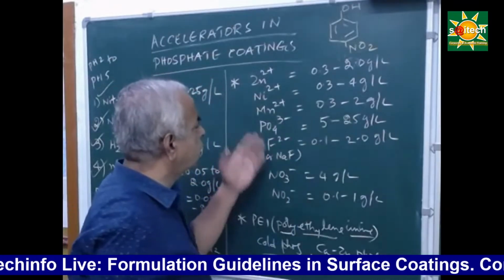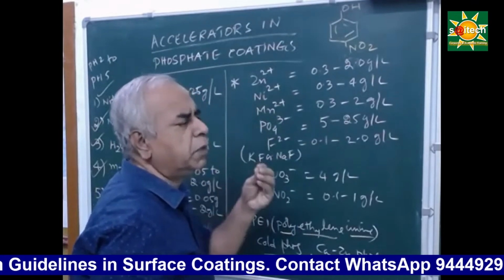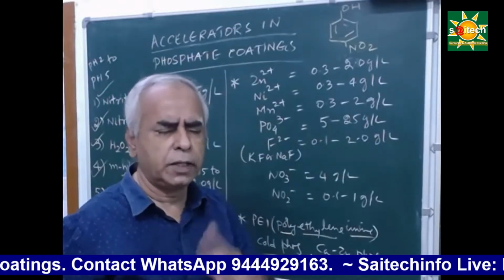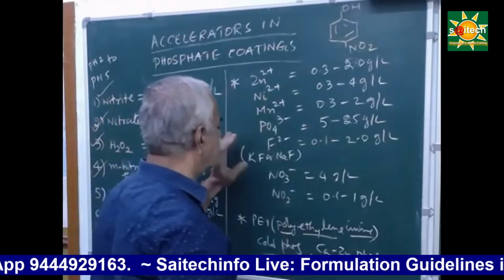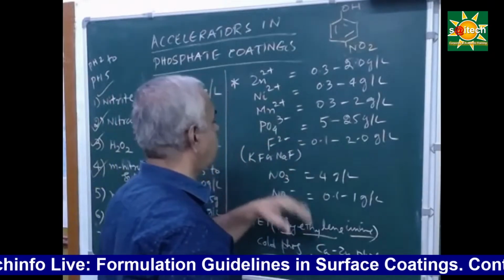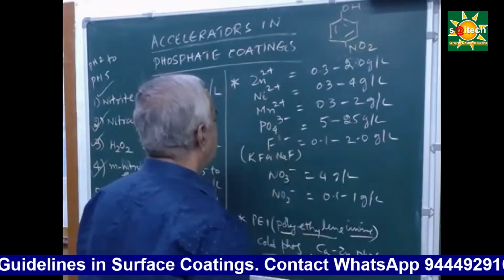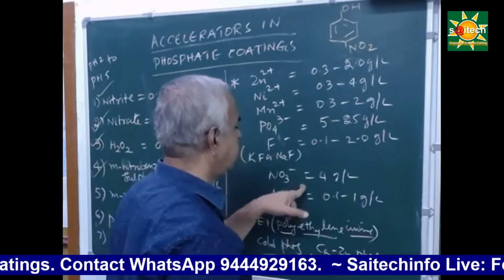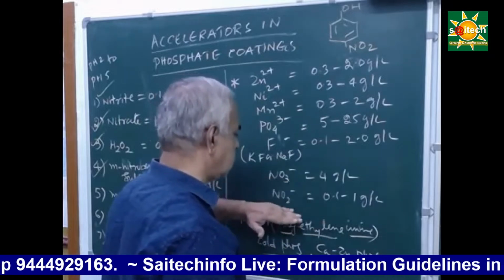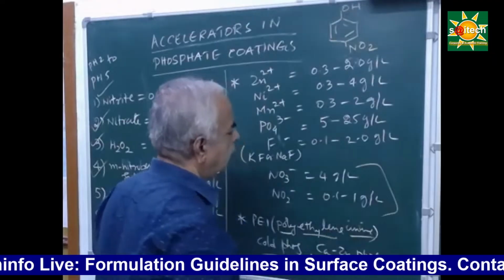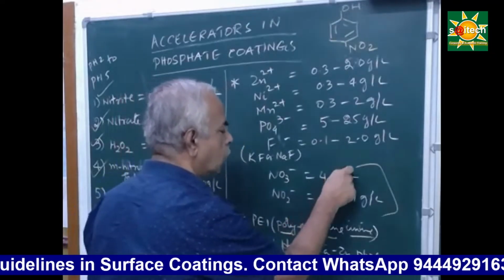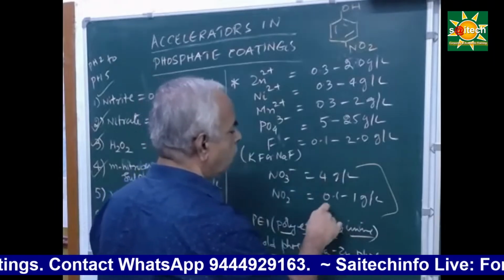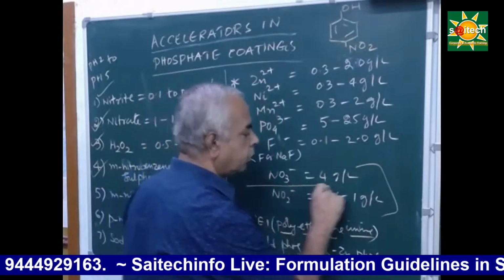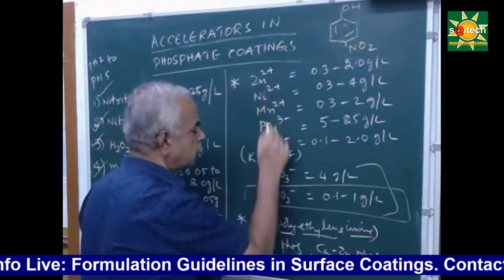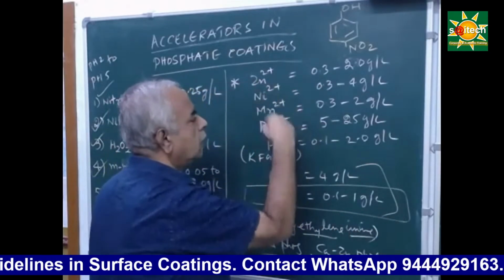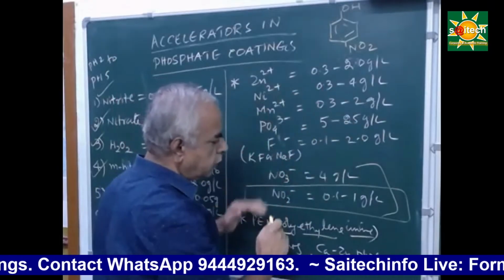This phosphate solution bath will be very nice, totally greenish, and very excellent. You have to add sodium or potassium fluoride, F minus ions, and then NO3 minus ions, nitrate, and this is nitrite. Just compare the concentration. Here nitrate will be more, 4 gram, whereas nitrite will be very little, 0.1 to 1 gram, and it should be given as a separate pack only. You should not mix it up with this, but you can mix nitrate along with the parent solution. So always try to give a 2-pack solution.